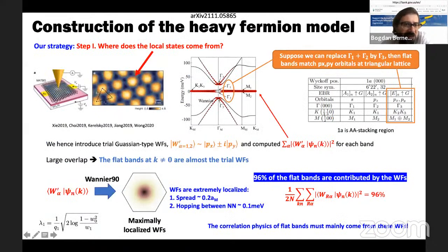So we understand the model is topological, so you cannot write it down in terms of localized states, but we also see the experiment. And the experiment clearly shows us that there are localized states in it. So we can ask, where do these local states actually come from? Now, if you look at the Bistritzer-MacDonald model, or the graphene model, instead of taking just these two flat bands here, you take the next 6 bands, and you only need this energy range. By the way, this energy range is smaller than the Hubbard U in the problem, meaning this band gap experimentally is smaller than the Hubbard U, so you're justified in taking these.